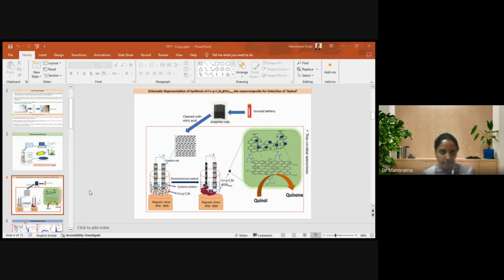These two rods are dipped in a cysteine solution, which is a kind of amino acid, plus the cobalt-doped graphitic carbon nitride solution, and in this combined electrolyte, when we put the two rods and apply the current, the graphene nanosheet is prepared by reducing the anodic graphitic rod. Because cysteine molecules and cobalt-doped graphitic carbon nitride are there in the solution, we got this arrangement: graphene nanosheet combined with the cysteine molecule, and graphitic carbon nitride interacting with the graphene nanosheet through pi-pi interaction. So these are totally non-covalent interactions, and this nanomaterial has been further utilized for the electrochemical sensing of quinol. Further, we have characterized this prepared nanomaterial with FTIR, Raman, and XRD.